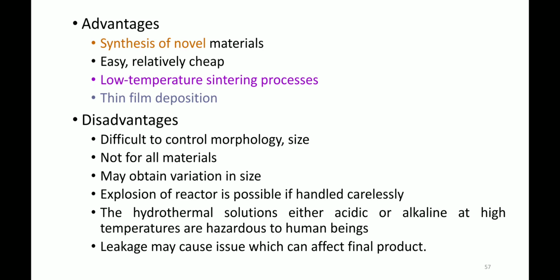This is because the system is very sensitive to temperature and pressure. Even a 20-30 degree fluctuation in the temperature may change the pressure inside a lot, which will dynamically change the formation of the nucleation and growth of the nanomaterial.